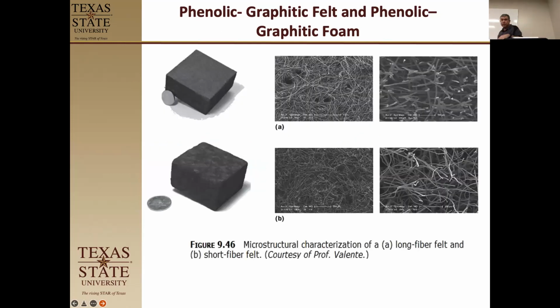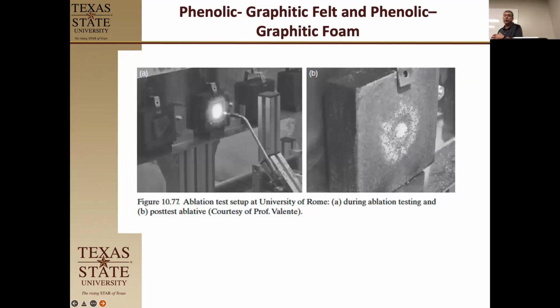Okay. So what you can do is you can make these things. And if we look at the first one, it's the long fiber felt that makes this fluffy little block brick here. And the fibers are not oriented in any specific order. And then this is the short fibers here. So those have longer persistence length than these. These have the shorter one. But I thought it was neat that they actually showed the foam thing.